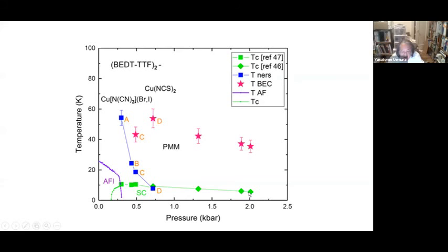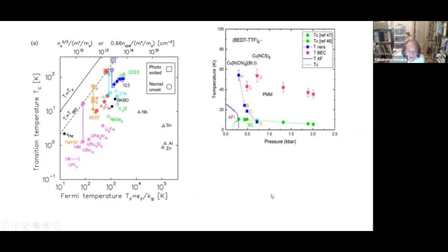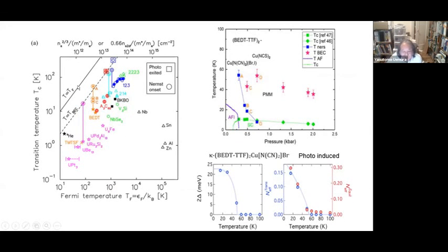And you have the superconducting state. And we measured superfluid density by mu-SR and other techniques, and it is giving this hypothetical BEC-like temperature scale. And the Nernst effect is happening here, but again, it is quite rapidly reduced in the overdoped region. So this is the trajectory of the Nernst onset temperature. And Andrea did his measurement, and as you probably heard, his onset temperature is about 60 Kelvin. And so this is Andrea's phenomenon point. And it is, again, very close to this hypothetical Bose-Einstein condensation, right? Okay, so this gives our photo-induced point here for the BEDT superconductor.